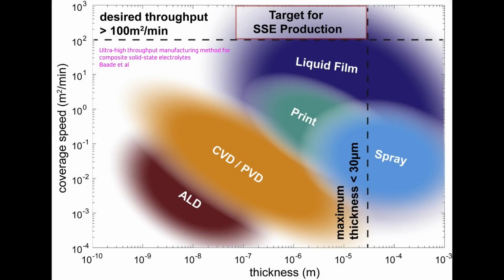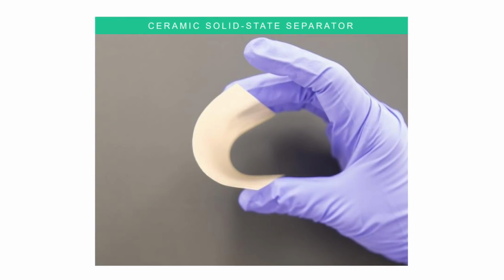The next thing that usually makes solid-state batteries expensive is that they require expensive manufacturing techniques. QuantumScape solves this problem by using a solid electrolyte that comes in the form of a freestanding ceramic sheet rather than a complex coating process. They also claim that their ceramic sheets are robust and flexible. Typically, any kind of manual handling, let alone bending, will introduce cracks into a solid electrolyte, creating defects which cause the battery cell to short out. I'd be curious to know if the solid electrolyte separator in this image was still able to be used in a battery cell. This much bending would usually crack many solid electrolytes, causing the cell to fail.